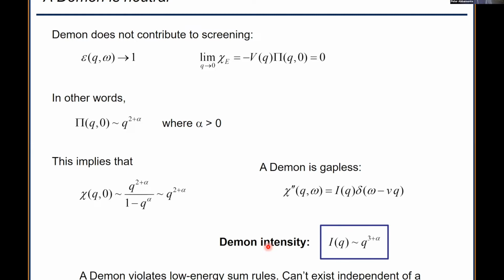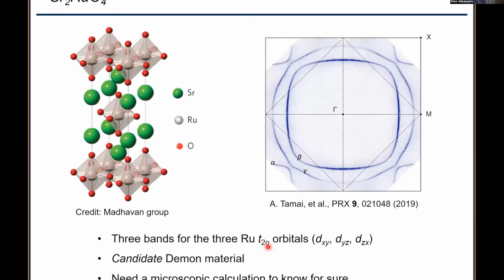12 minutes, good. Okay, so strontium ruthenate. Strontium ruthenate has 3 Fermi surfaces, not 2, and they owe their existence to these 3 different ruthenium T2G bands. So I would call it a candidate demon material. It's not obvious it would necessarily have a demon. For one thing, it has another band hanging around that could interfere, or maybe it could even create 2 demons, I don't know. But to know if strontium ruthenate has a demon, you have to do a microscopic calculation, which Pines never did.